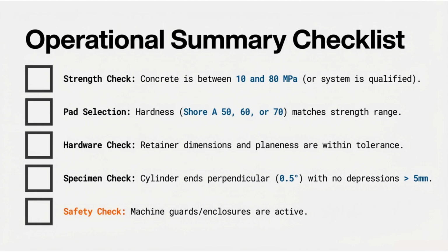Now we bring it all together in one checklist. This is the slide I would post on the wall next to the compression machine. Let's walk it. Strength, check. Concrete is between 10 and 80 megapascals, or system is qualified. Pad selection. Hardness check. Shore A 50, 60, or 70 matches the strength range. Hardware check. Retainer dimensions and planeness are within tolerance. Specimen check. Cylinder ends are perpendicular within 0.5 degrees and no depressions greater than 5 millimeters.